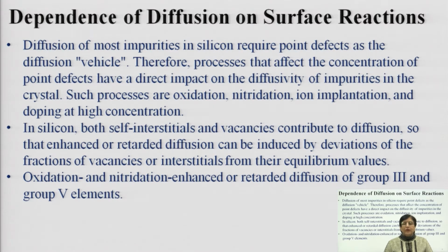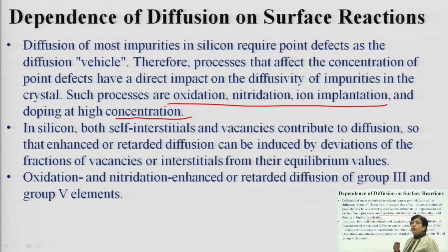Such point defects will also be impacted by oxidation, nitridation or ion implantation. You can enhance the movement by such processes, and you can attain a high concentration of the dopant profile. So, whatever dopant profile you are going to have can be enhanced using these techniques.